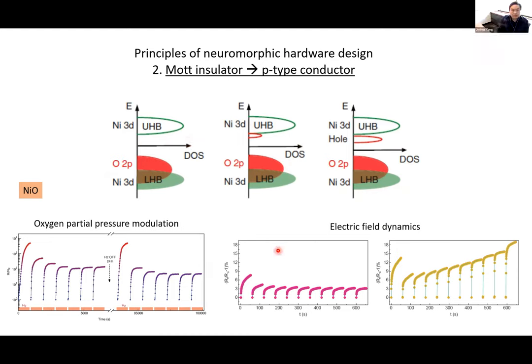The resistance change here is minimal from hydrogen. It is entirely through oxygen defects. Sorry, I should have been more clear. So here you have metastable oxygen defects, and instead of vacancies, you have interstitials, and then you can have P-type doping. So the mechanisms are slightly different. In nickel oxide, you can see in this plot the electric field dynamics. At least in the experiments we did, we found that the oxygen dynamics was much slower, milliseconds and slower. We could not see any response faster than that. I don't know if that was because we were focusing on metastable defects.